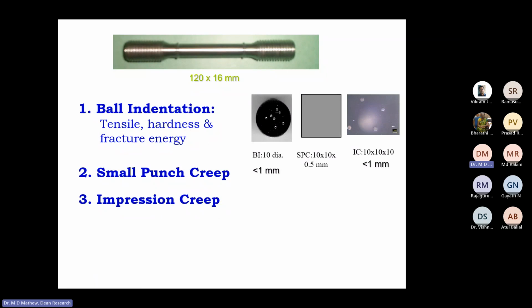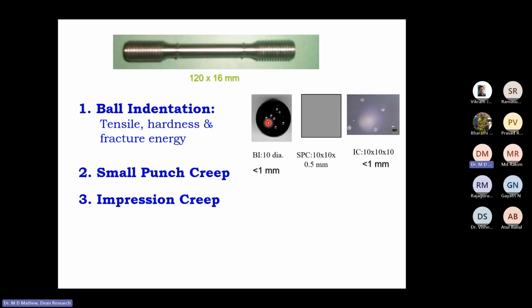What you see here are 3 specimens. This is a 10 millimeter diameter specimen, about 5 millimeter thickness. This is a ball indentation sample. You will find that already there are about 7 tests done. And each of these depth of this impression will be much less than 1 millimeter.